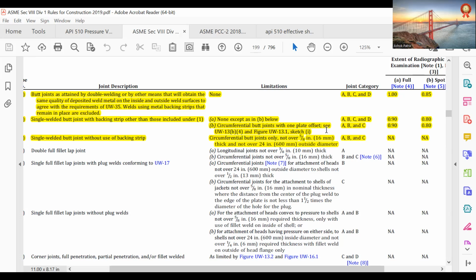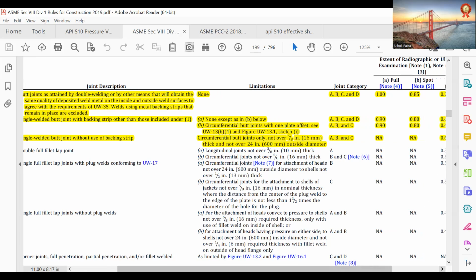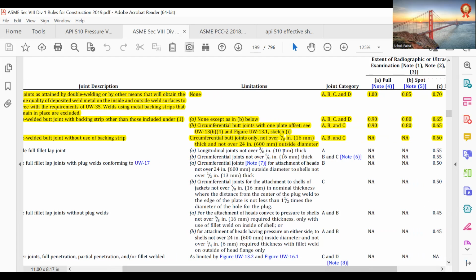Circumferential butt joints with one plate offset. Already we've seen the sketch. Circumferential butt joints only, not over 16 millimeter thick and not over 24 inch, 600 diameter. So there are three things. First one, except as B below: ABCD 0.9, 0.8. Even this one with one plate offset is the same thing. Don't have to bother too much about this. 0.65 is the last one. And if it is a circumferential butt joint only, not over 16 millimeter thick and not over 24 inch, 600 outside diameter, then it is not applicable. Not applicable is 0.6.